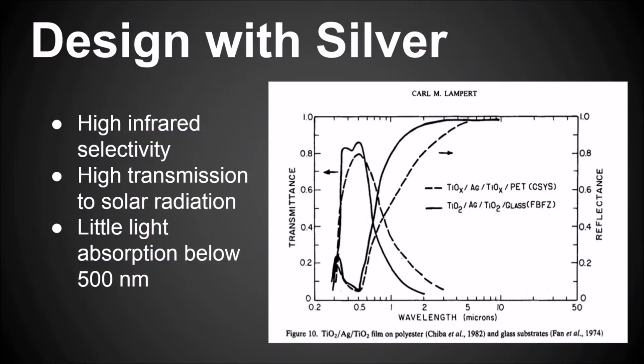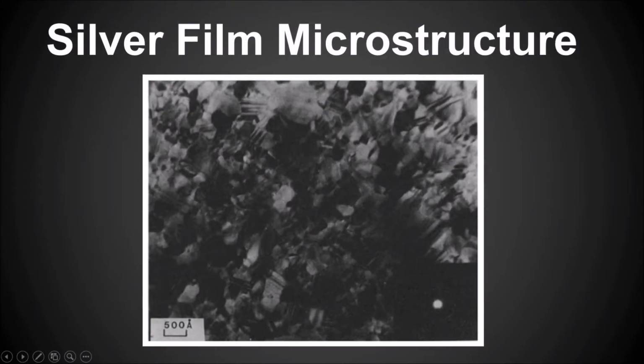So as we see, we get exactly what we want, a high transmission between 350 and 800 nanometers. Visible light wavelengths are in the range of 390 to 750 nanometers. Anything above that, we see very high reflection by the silver for a micron and above. Other materials such as gold or chrome show significant absorption below 500 nanometers, and so we're unable to take advantage of the visible light that's coming through, and that's actually reflected in alternate materials. Here we see an image of the microstructure of the silver film as imaged by a transmission electron microscope.